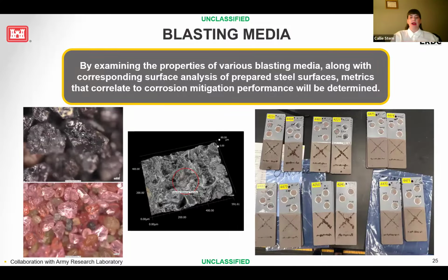Okay, so another cool thing that we are working on is some blasting media. In order to apply some form of a coating to a substrate, you need to have some sort of surface profile. That way, when the coating is applied, it's not applied to a straight surface, and it gives the ridges and the peaks and valleys for the coatings to be able to really seep in and actually adhere better to the surfaces. So one thing that we're looking at is if we use different types of blasting media, are we able to find a correlation to mitigating properties?